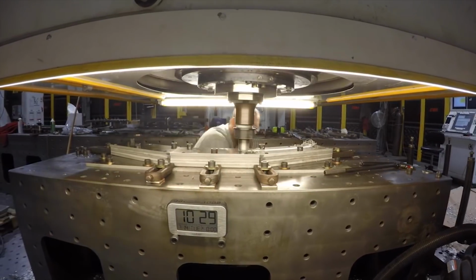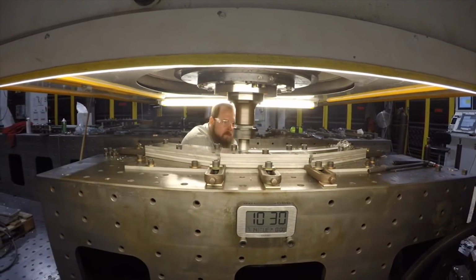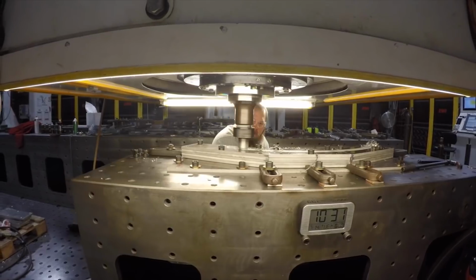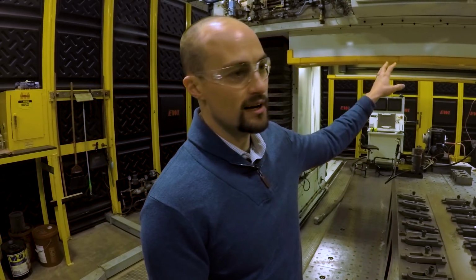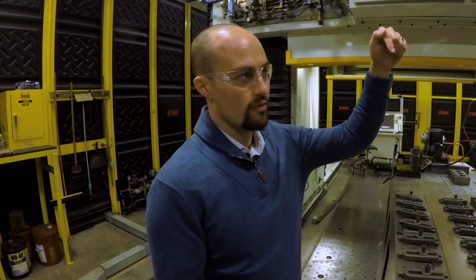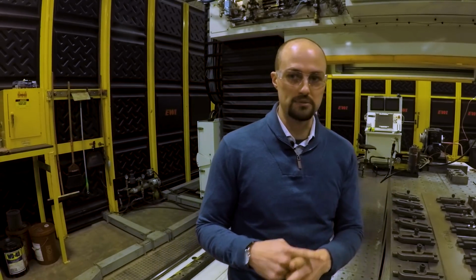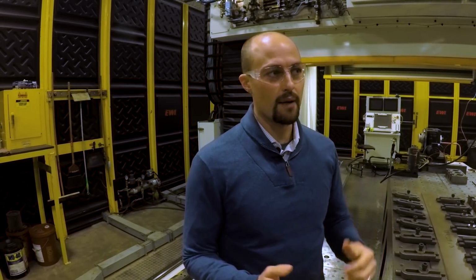Even though we get hot and soften the material, this is a very high loading process. The thicker the material, the more loads that we have, and depending on the material grade as well. This machine is one of the most capable machines in North America. We can go in the Z-axis, so downforce, up to 60,000 pounds of load. X and Y up to 15,000 pounds, and about 1,800 foot-pounds of torque.